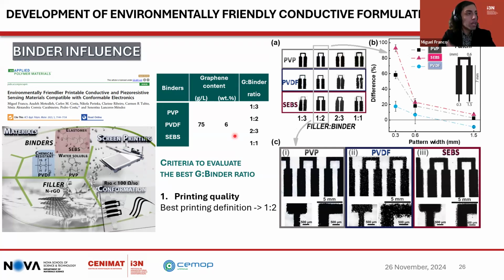So you expect that using a higher binder amount like this one, you should get a higher adhesion, but with the trade-off of lower conductivity. But if you are above the percolation threshold, there is no significant change in sheet resistance, however the adhesion properties of the films tend to worsen a lot.